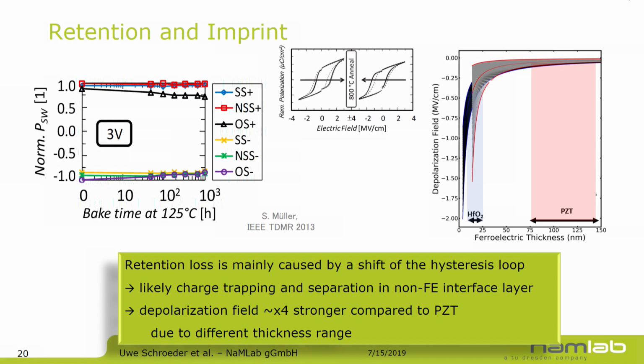And this is not coming from a real depolarization and a drop in remanent polarization. It's just coming from, as you can see here, a shift of the hysteresis loop. And this is mainly due to charge injection into the interfacial layer. If you think of your hafnium oxide, which is on the order of 10 nanometers, and you have possibly interfacial layers on the order of 1 nanometer, there's a strong field to inject charges into this interfacial layer, which is leading to this shift of the hysteresis loop.